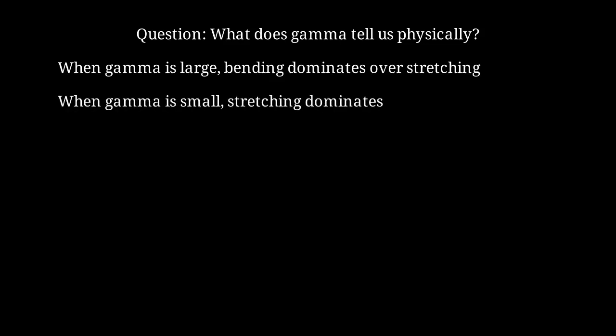You might wonder, what does gamma tell us physically? It's the ratio of the shell's bending energy to its stretching energy. When gamma is large, bending deformations dominate over stretching. The shell buckles more easily with complex shapes. When gamma is small, stretching deformations dominate. The shell resists buckling and deforms uniformly.